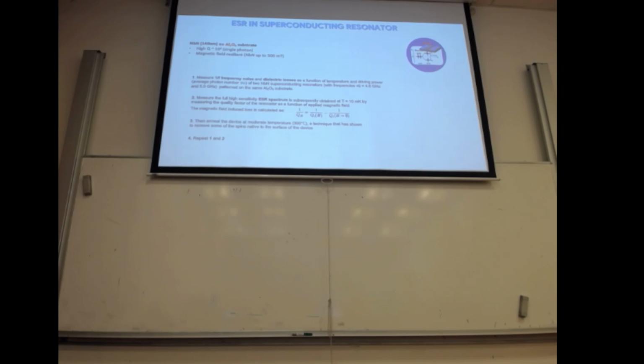And he has 2 tools that he can use to understand this. Of course, one is just to measure the flicker noise of the resonator that we were discussing last time. And the other is to measure the loss tangent, so the dielectric loss. He built 2 resonators and complemented this measurement with other measurements done with electron spin resonance, in which you can see what kind of species it has. He always measures the quality factor, with and without an applied magnetic field, so he can evaluate the contribution of the noise due to the spins.